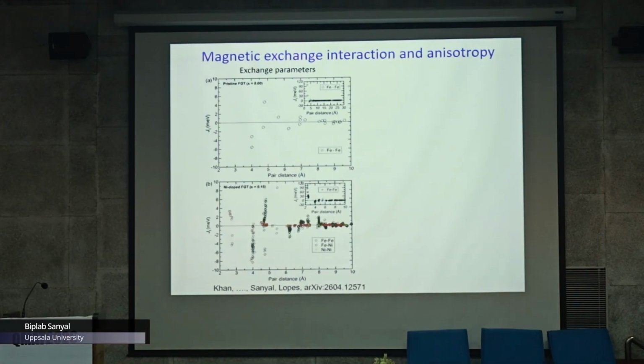But the interesting point is that when you have nickel doping, the nickel can go to a substitutional site, and nickel can also go to the intercalation sites in the van der Waals gap. You see different types of exchange interactions with all the different pairs present in the system. They are plotted here. So along with all the positive numbers, you see a lot of negative parameters, the antiferromagnetic exchange parameters, that occur. And as a result, if you sum all these exchange parameters, you see that the resulting effective exchange decreases, and also if you do a Monte Carlo simulation, the Curie temperature decreases.